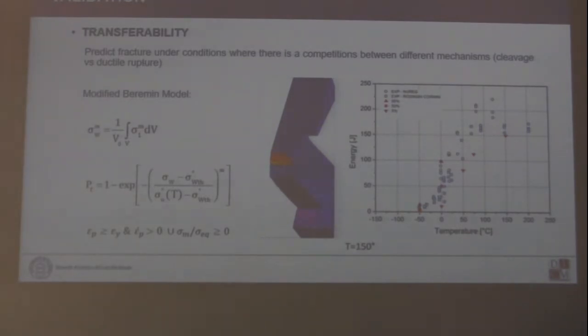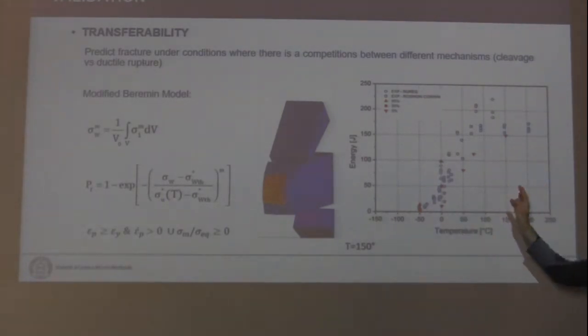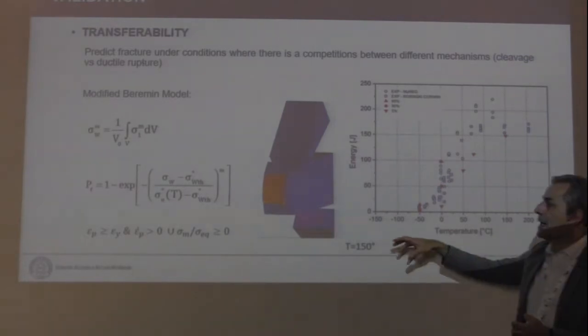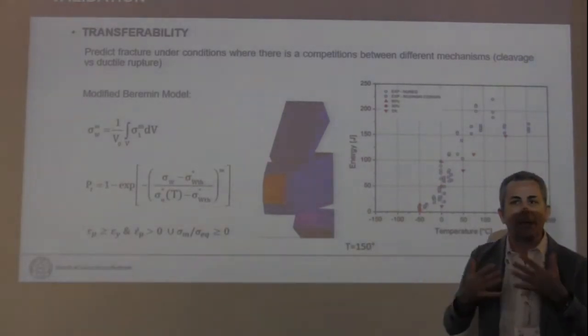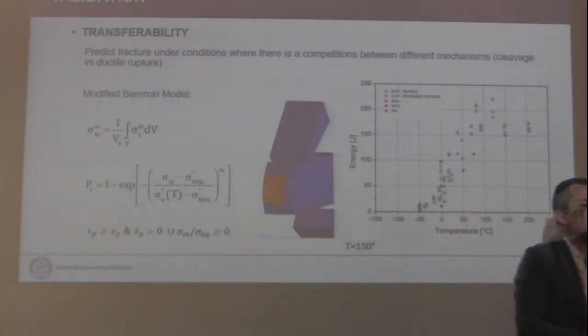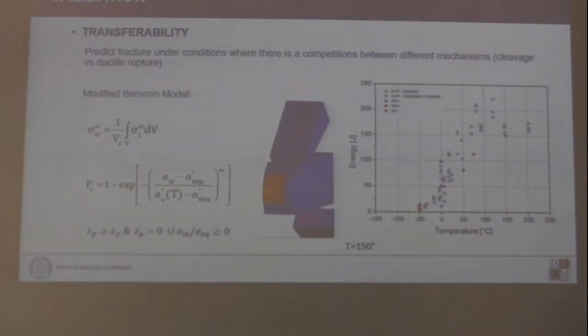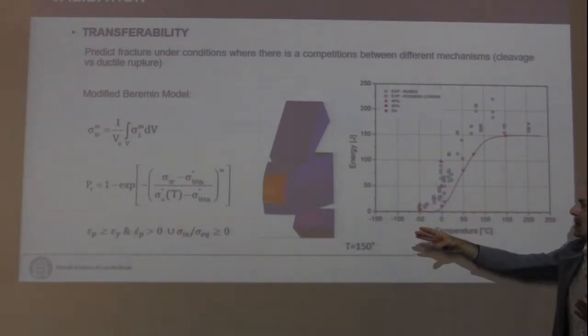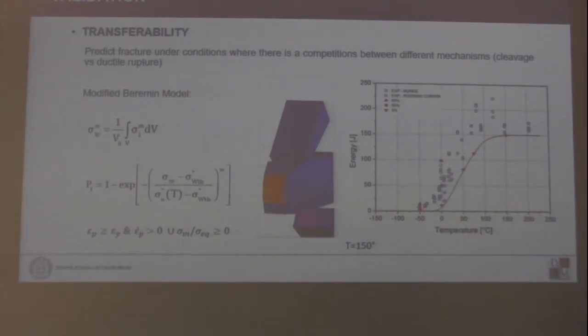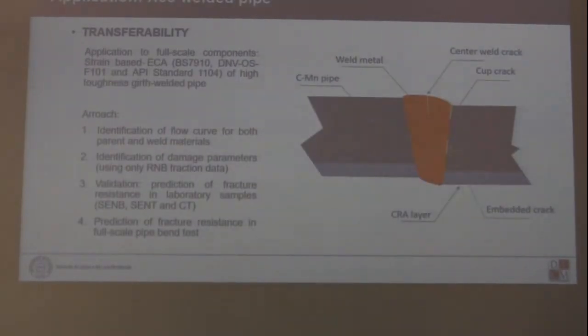Another possibility is transferability when you want to describe a failure process in which two mechanisms go at the same time. This is the case, for instance, for the ductile to brittle transition using the Charpy notch, in which you have brittle fracture and ductile fracture competing. And again, if you use this damage mechanics concept together with, for instance, a probabilistic model such as the modified Beremin model, it is possible to predict, without the need of experiments, just providing the material model parameters, the lower bound and the scatter band in the Charpy energy curve.